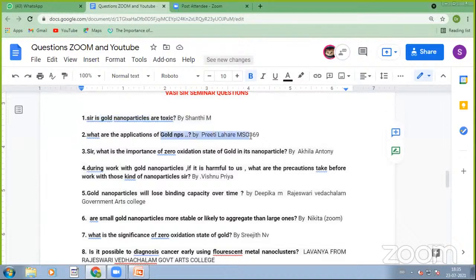Applications of gold nanoparticles, there are many. Already I discussed. What is the importance of the zero oxidation state of gold nanoparticles? If the zero oxidation state is there, then only it is stable. That is metal nanoparticles. If it is not zero oxidation state, it's still ions. Gold chloride has the Au3+ ionic oxidation state. Au3+ should be reduced using reducing agents. There are many reducing agents. I forgot to mention strong reducing agents and weak reducing agents. Strong reducing agents are sodium borohydride, hydrazine, and lithium aluminum hydride.